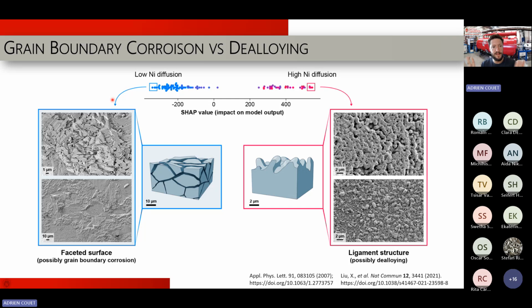So we looked at the facets or the morphology of the surface, and we noticed that for low nickel diffusion, we tend to have more faceted features. For high nickel diffusion, we tend to see more ligament morphology. So potentially, the nickel diffusion is playing a role on the morphology of the surface that then is connected to the corrosion rate of the alloy.